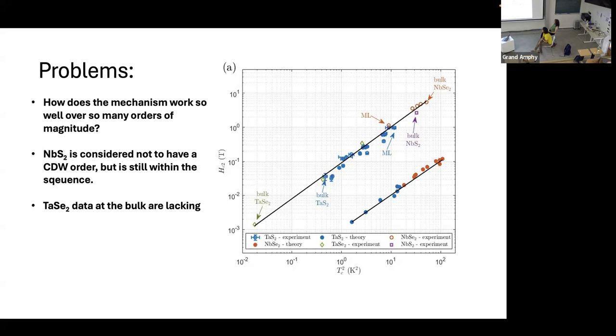No, there is no gate. This is a tunnel junction, and actually many of these data sets were measured differently. Some of them are transport experiments, some of them are tunnel experiments, and some of them were measured by neither transport nor tunneling, but by some kind of electromagnetic inductive response, because the Hc2 was so small. So this data is agnostic of the way it was measured.